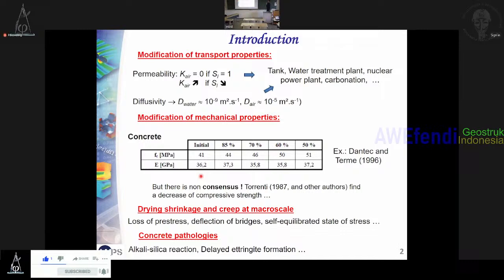And for diffusivity, it depends. If you are looking to the diffusivity of ions, if you have water, you have the most important value of diffusivity. And when your concrete is drying, the diffusivity is decreasing. So it's quite clear. But if you look to concrete mechanical properties, you will find whatever you want. So most authors find an increase of mechanical properties due to drying. I will explain why a little bit further.